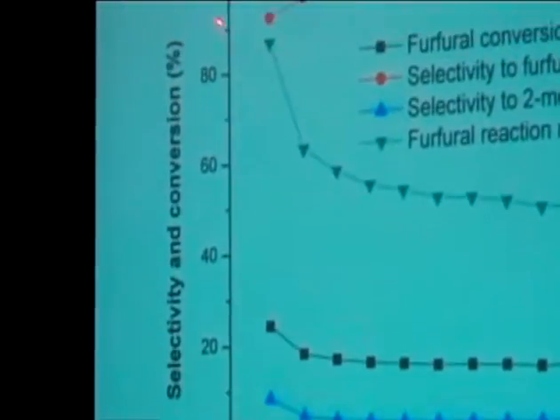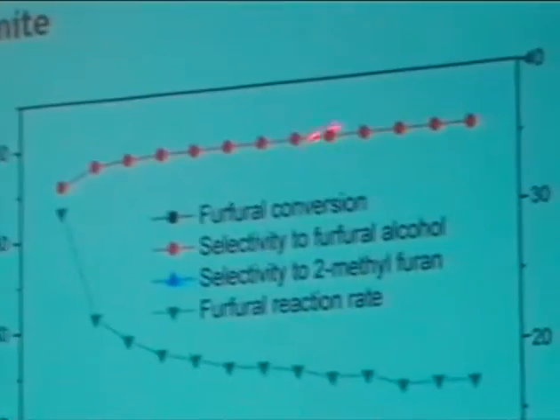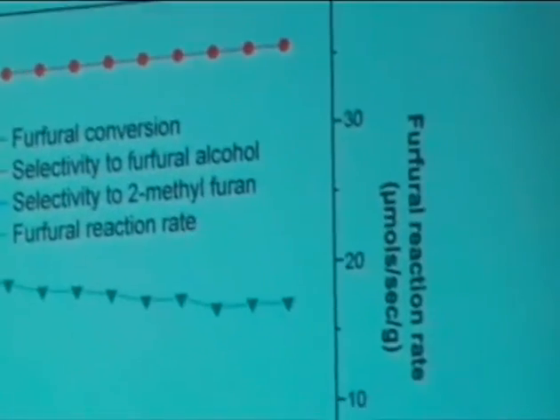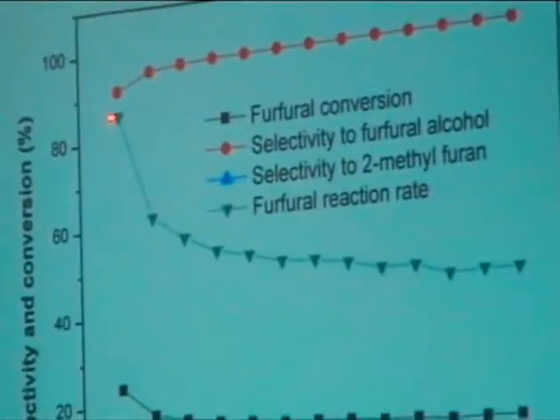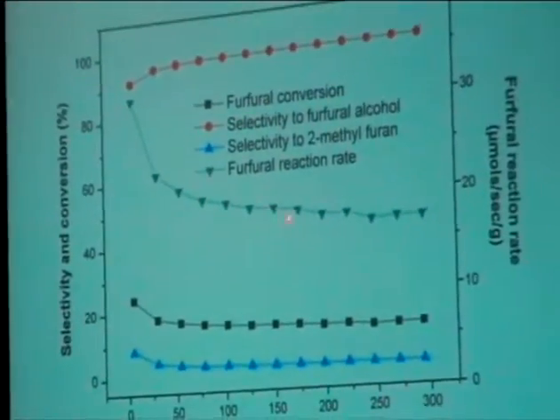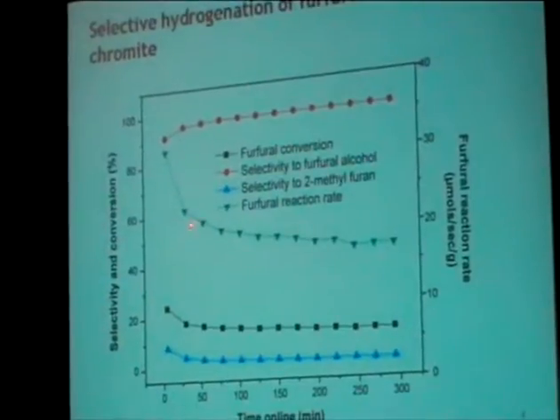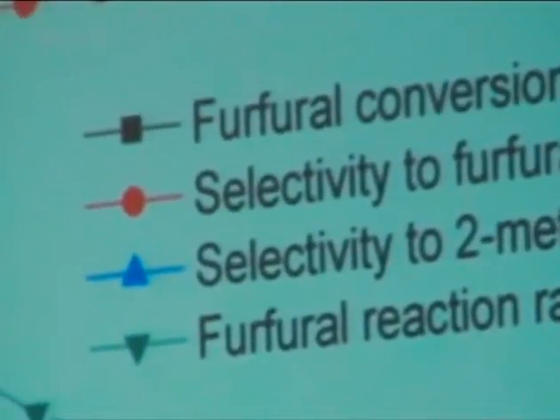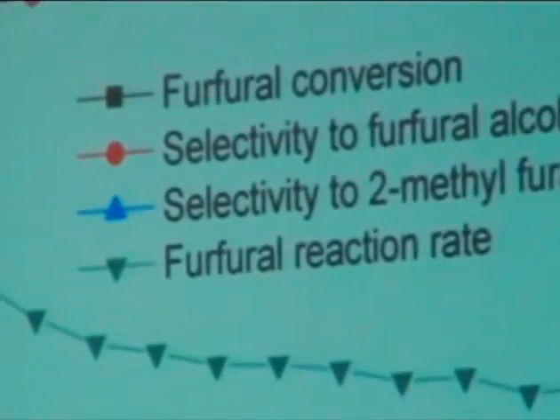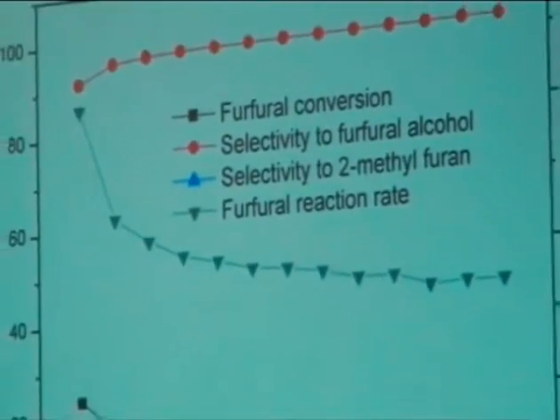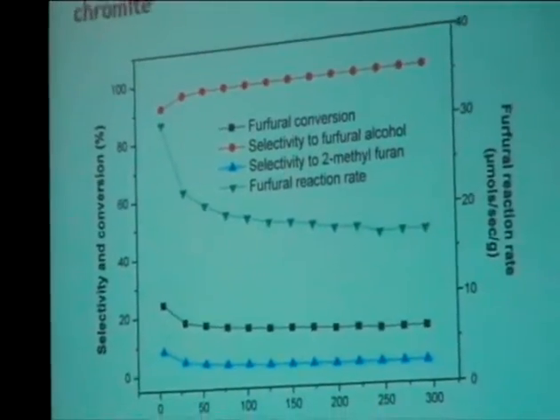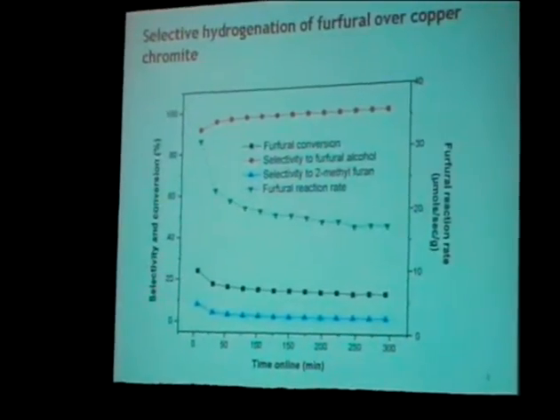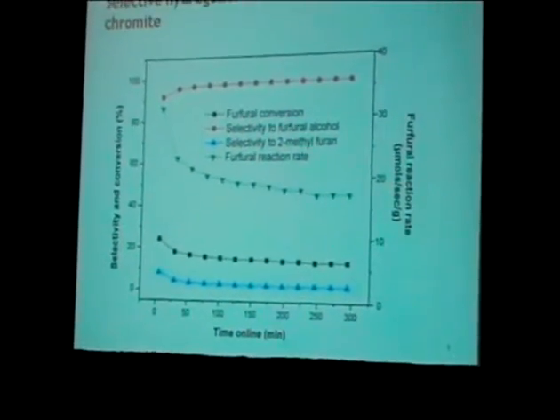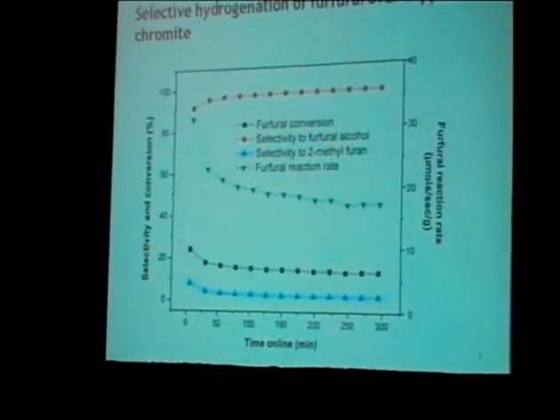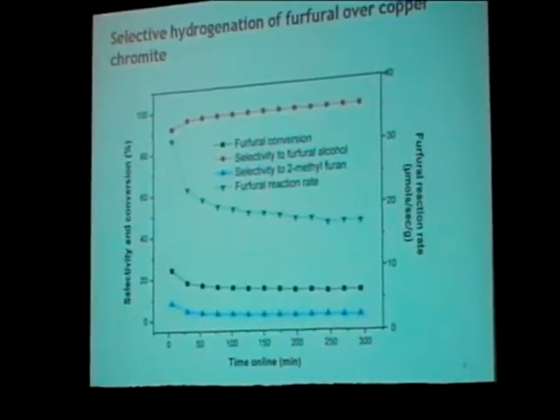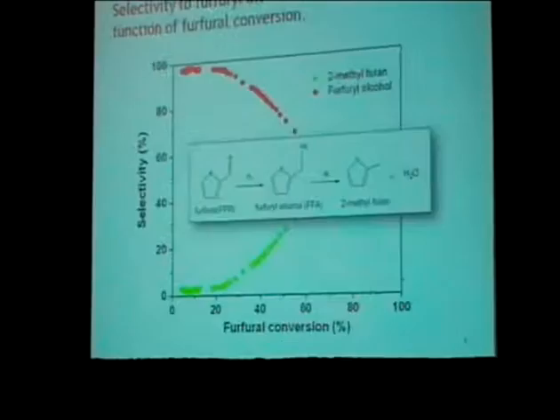This is a plot of the furfural conversion rate and the selectivities for the various components here. You can see that the selectivity to furfuryl alcohol is quite high for this reaction at relatively low turnover frequencies. But most important here is the reaction rate starts out high and drops immediately, and it continues to drop over the course of the 300 minutes on stream that you see here. If we continue this out for several days, it continues to drop over the course of the time that we're looking at. So part of the talk today is that we're very interested in the mode of this deactivation and how we can mitigate that deactivation with various types of chemical treatments.